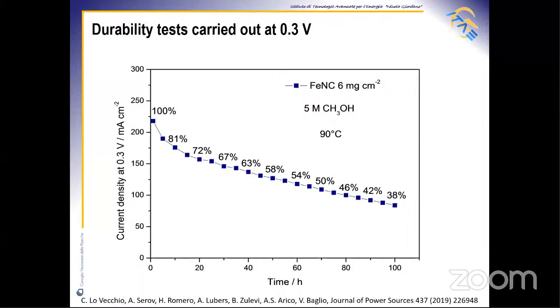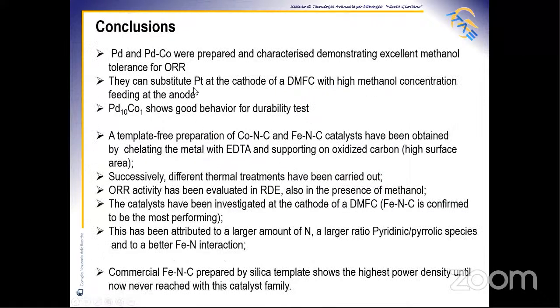In direct methanol fuel cell, the current density shows initially a rapid decrease of performance with a loss of power density, and then the degradation is decelerated. In conclusion, in the first part, we talked about palladium and palladium cobalt that were prepared and characterized, demonstrating excellent methanol tolerance for oxygen reduction reaction. They can substitute platinum at the cathode when working with high methanol concentration. The palladium 10 cobalt 1 shows good behavior in the durability test.